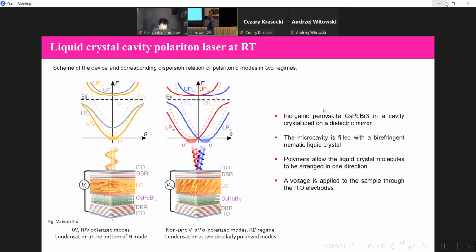So our device will be a combination of this and the liquid crystal. To do it, we need two more things: the polymer with rubbing to align the liquid crystal in a good direction, and the ITO electrodes to have a chance to tilt the liquid crystal.